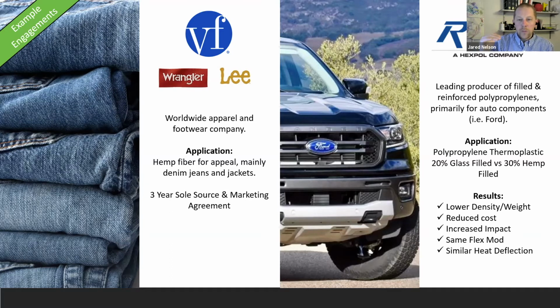So the weight dropped, right? The density reduced because hemp weighs half as much as glass. It weighs less than the polypropylene. And oh, by the way, we bumped it up by 10% compared to the glass. So this product got significantly lighter. It was significantly less expensive, again, because the hemp filler itself was less expensive than the glass or the polypropylene. We saw an increase in the impact resistance, the stiffness, and the heat deflection remained similar.